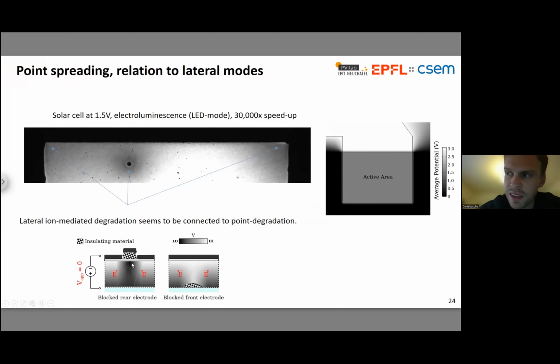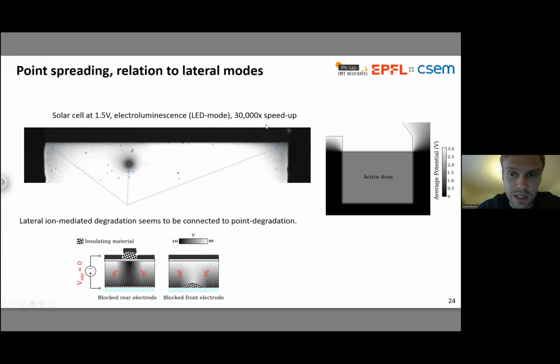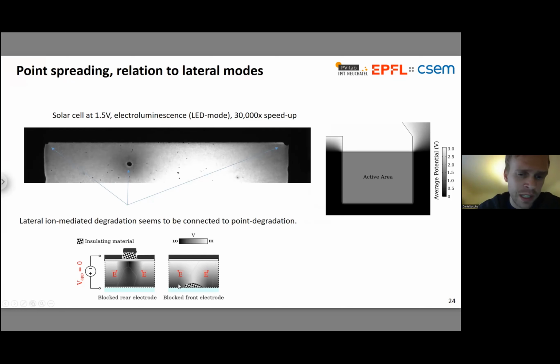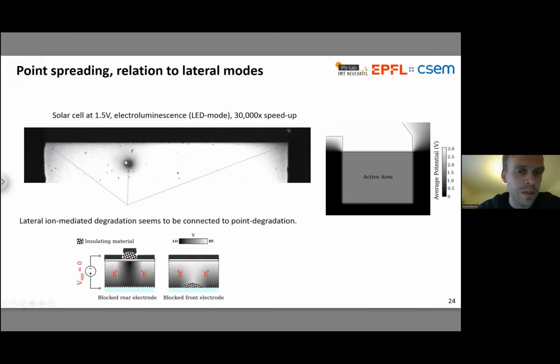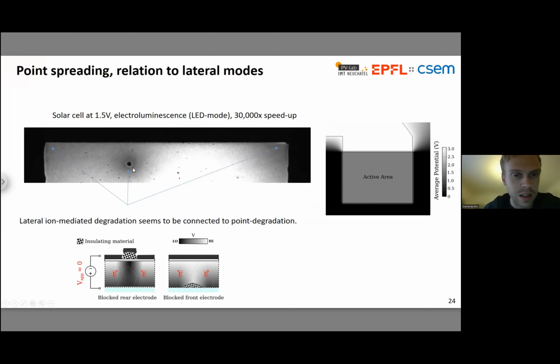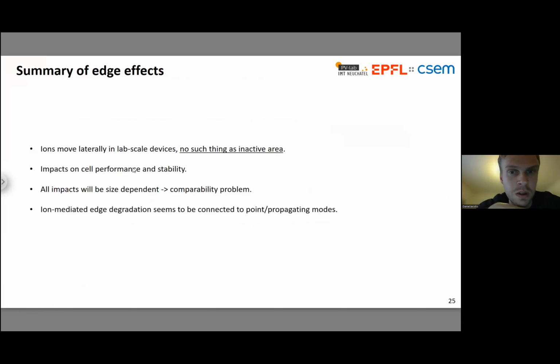I think you can understand that if the contaminant particle here is either obstructing the top or the bottom electrode, because in that case you would expect the formation of these lateral electric fields, and you might then see precisely the same form of ion-induced degradation that we see at electrode boundaries happening around these contaminant particles. So you can potentially understand this theoretically, that's perhaps what's going on.